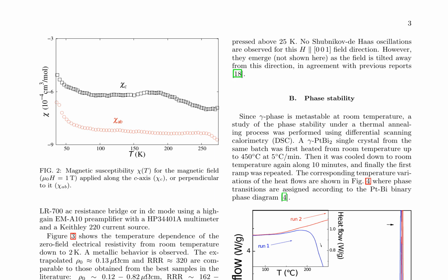The magnetic susceptibility, χ(T), exhibits a pronounced temperature dependence for magnetic fields applied along the c axis, χ_c, and perpendicular to it, χ_ab, as shown in Figure 2. Measurements were conducted using an LR700 AC resistance bridge or in DC mode with a high-gain EM-A10 preamplifier and a Keithley 220 current source. The temperature dependence of the zero-field electrical resistivity, depicted in Figure 3, reveals a metallic behavior with an extrapolated residual resistivity, ρ0, of approximately 0.13 microohm cm and a residual resistivity ratio, RRR, of around 320, comparable to the best samples in the literature.